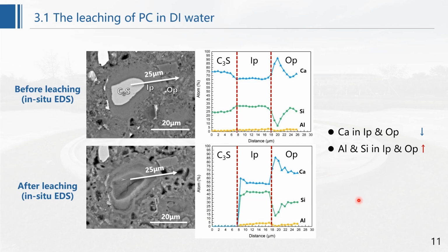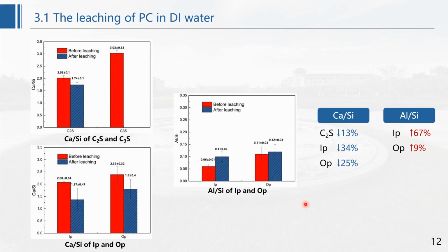Here are EDS results of PC paste before and after leaching. We can see that after leaching, the relative content of calcium in inner product and outer product both decrease, while the relative content of aluminum and silica in inner product and outer product increase. Then we analyze the composition of different phases.